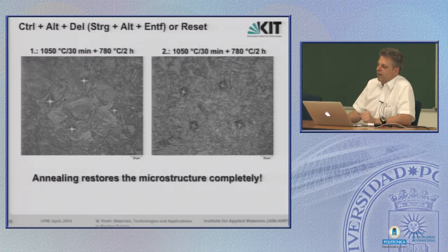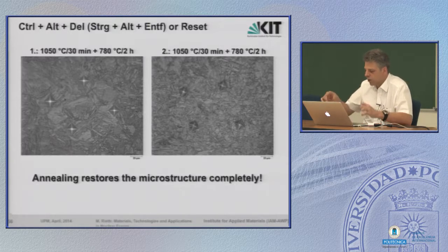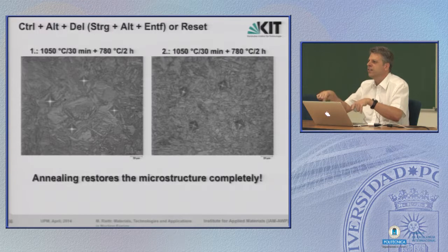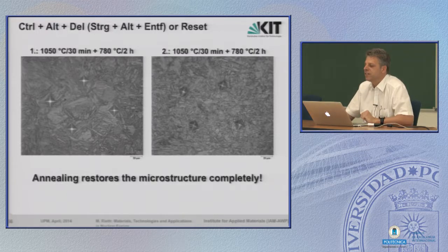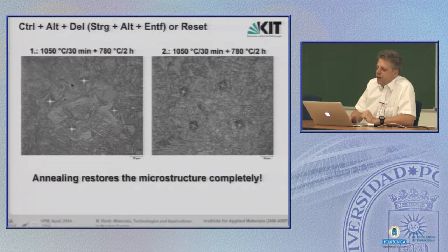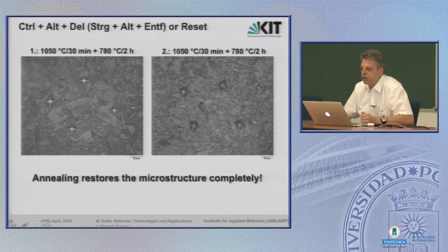Well, what I call the implemented reset button of Eurofer or martensitic steels, or, well, on some computers it means Control-Alt-Delete. You know what happens. It's a restart, a reset. We have tested this for Eurofer. Here we have marked a typical prior austenitic grain with the internal martensitic structure. We have marked this with four hardness imprints, and then we have performed the same heat treatment again, annealing, quenching, tempering. And after that, here are the four hardness imprints, and the structure has completely reshaped, restored.